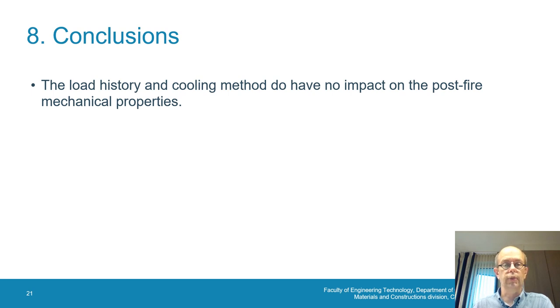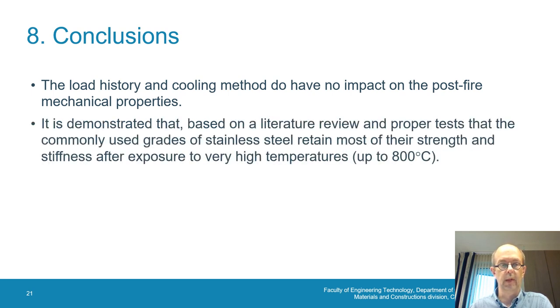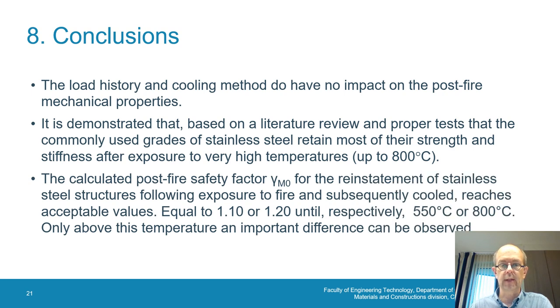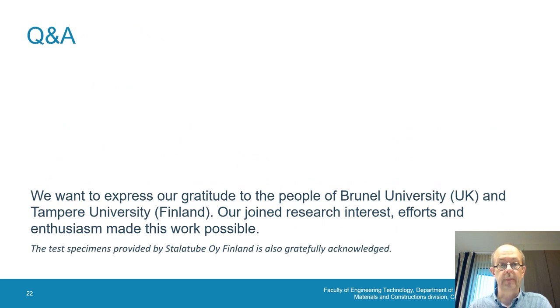To end, some conclusions. The load history and the cooling method do have no impact on the post-fire mechanical properties. And it is demonstrated that based on the literature review and statistical data processing, that we can retain most of our mechanical properties up to 800 degrees Celsius. Moreover, it seems that the safety factor can be kept constant at 1.1, the one of ambient conditions, up to 550 degrees Celsius, and then should be slightly adapted to 1.2 at the moment that the structure has been submitted to temperatures till 800 degrees Celsius. Above, then it becomes more problematic. Time for questions and answers, and thank you for your attention.